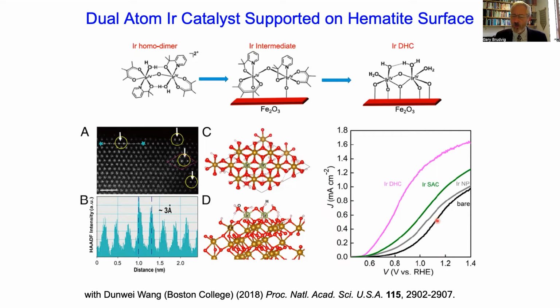But in this case, we're comparing not only bare hematite here in black, but iridium nanoparticles attached to the surface of the hematite, which slightly improve the performance, or single iridium atoms on the surface, which improve the performance a little bit further. But the dinuclear heterogenized catalyst, or DHC, dramatically improves the onset voltage for light-driven water oxidation. The surface now can be imaged using high-resolution TEM, and this is showing the hematite lattice where we